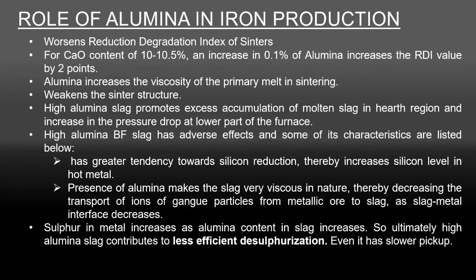Some of these are it has greater tendency towards silicon reduction, thereby increases the silicon level in the hot metal. Presence of alumina makes the slag very viscous in nature, thereby decreases the transport of ions of gangue particles from metallic ore to the slag. Sulfur in metal increases as alumina content in the slag increases. So ultimately, high alumina slag contributes to less efficient desulfurization. So now my partner Vishal Vemla will take over.